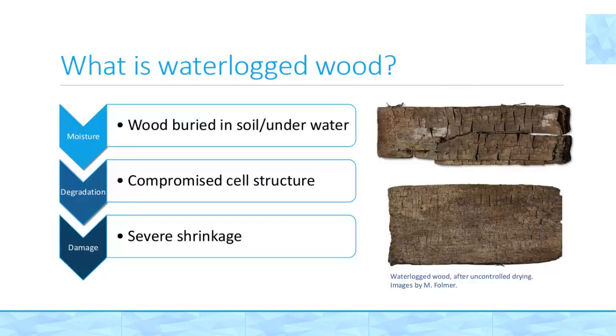So what is waterlogged wood? When wood becomes either buried in the soil or it sinks to the bottom of a river or a lake, it becomes fully saturated with water. The wood eventually becomes waterlogged. There is no more air present in the wood. When stored in these wet conditions, degradation mechanisms will occur differently compared to wood that is kept above the surface. Though waterlogged wood will degrade much more slowly, this degradation still occurs and it results in a compromised cell structure.